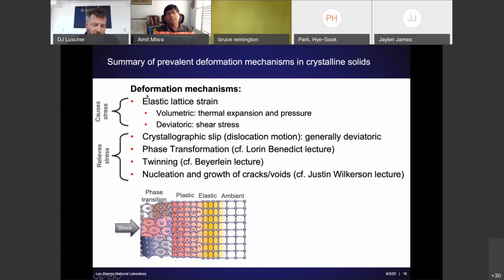If we impose a deformation and we cannot accommodate those imposed deformations by stress relieving mechanisms, then we're left with high stresses. And in fact, that's usually what happens in the wake of a shock wave in a transient manner. And so some of the inelastic mechanisms, of course, are crystallographic slip, which is accommodated by dislocation motion, phase transformations, twinning, and the nucleation and growth of cracks and voids.